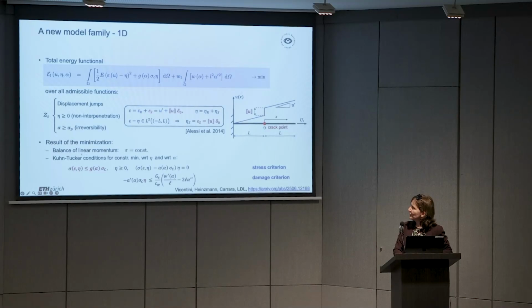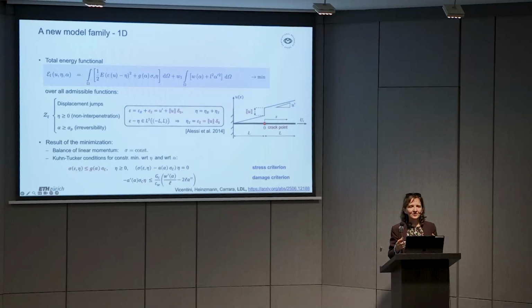So what happens from the minimization, this is maybe the interesting part, is that minimization with respect to u will give you the usual balance of linear momentum. Minimization with respect to eta, with this constraint, and with respect to alpha, will give you now two ingredients. Before I told you if you minimize with respect to alpha, you get a damage criterion. But now you're minimizing also with respect to eta, and this gives you a stress criterion. So this is, let's say, let's call it trick, so the way to introduce a strength notion into the variational model.